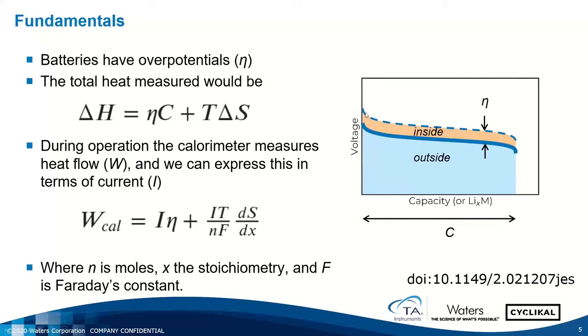So we have our equilibrium potential, sort of the zero current potential of the cell. And when we actually use a cell, the voltage, the potential that we actually see at the terminals is depressed, is lower than the equilibrium potential. And the blue area here corresponds to the work that we can actually extract from the battery and is measured outside the calorimeter. But the area here in orange will actually be dissipated inside the calorimeter and be measured. And this area would correspond to this overpotential here times the capacity.